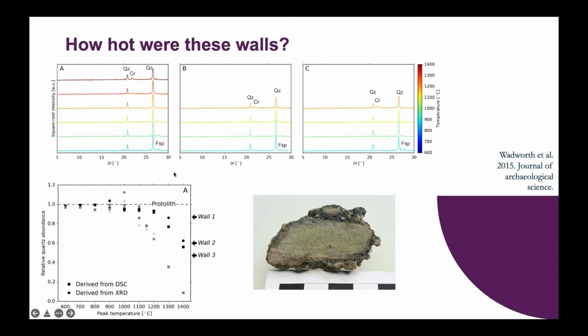A key question then is, how hot were these walls? So we did some in situ XRD measurements. This is an example from the sandstone vitrified wall, where we were tracking the decrease in the quartz peak at higher and higher temperatures, and the appearance of a cristobalite peak that replaces the quartz. Cristobalite is a high temperature polymorph of SiO2, so as quartz starts to break down, cristobalite forms, and that's tracking the partial melting.